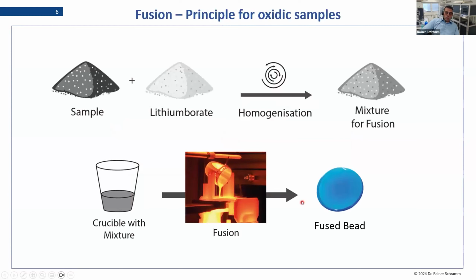Okay, so how do we do fusion? The idea is always that we need a glass powder, a glass where we want to dissolve our sample into. So we mix this glass powder together with the sample. And we have to make a good contact between both, so mix very well.